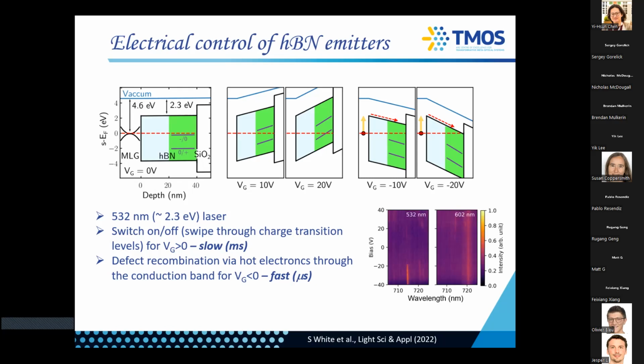You sit on an emitter here, you excite with the green laser, and it turns on around minus 20 volts. When you shift the laser to red, to 600 nanometers, which is less than 2.4 eV, you don't see anything. This is just a Raman signal, and you sit exactly on the same confocal spot. So it's a nice theory. We have absolutely no proof that this is actually what is happening, but all the ducks align, basically. So it looks legit.